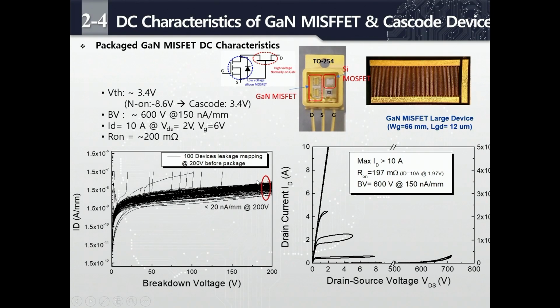After the device mapping, we select the devices and then package them to make an E-mode device with the cascode configuration. We use a silicon low-power MOSFET as the gate function, and the gallium nitride MISFET for high voltage, the normally-on gallium nitride structure. After that, we can operate the E-mode structure. It shows more than 600 volts breakdown and more than 10 amperes of current.